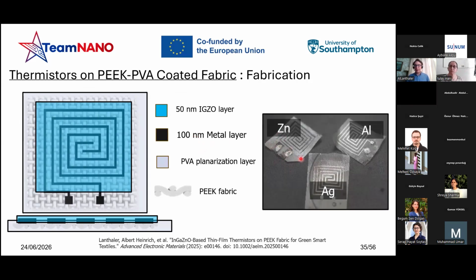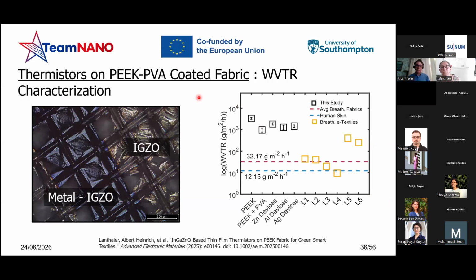We wanted to investigate 3 metals as electrodes, starting from the less benign one to the more natural-based one: aluminum, silver, and zinc, in that order. And as I mentioned, the sputtering technique also helps us to achieve one of the tasks I mentioned before. As you might remember from before, the planarization layer goes everywhere, coating pretty much the entire surface of the fabric, and also enclosing these very holes in the lattice, preventing the textile from still being breathable.